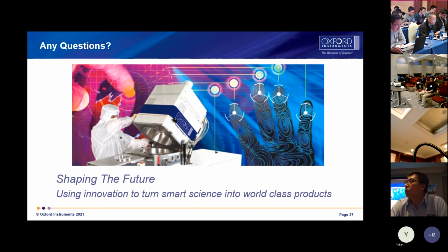So I think John, because he is the director of JWNC, at the moment, our three guys on the cluster, yeah, it's very difficult to get a very good recipe to dry etch, for example, the sidewall grating, because we have not found the window, the recipe window, with a little bit higher etch rate and also a good sidewall of the grating. At the moment our etch rate is very slow. Maybe using CH4, hydrogen and oxygen. A lot of our PhD students and postdocs have this problem. So maybe if your Oxford Instruments can help. We are happy to support you, no problem. Yeah, we can discuss the details. We take a lot of time to sort out this problem.